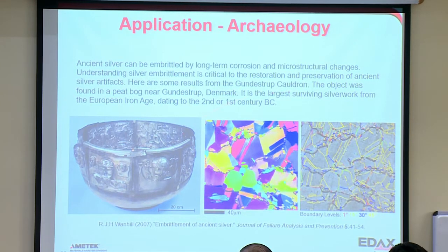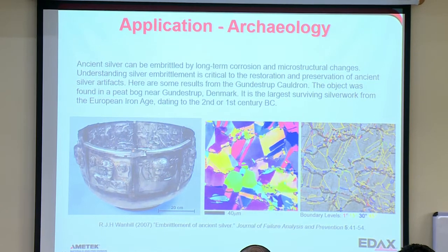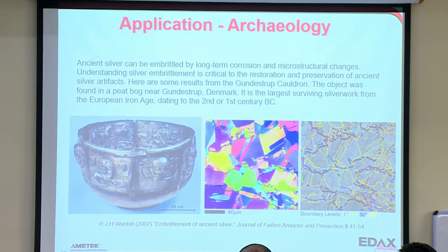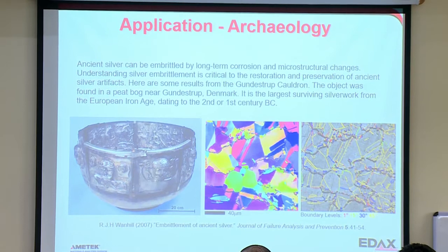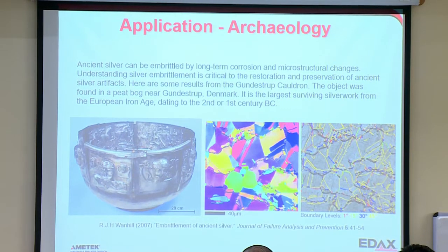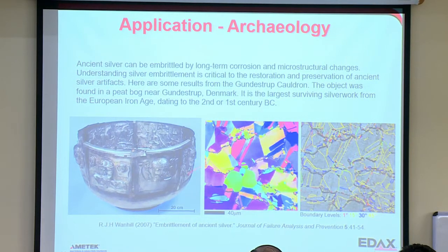called the Gundestrup Cauldron. It came out of the peat bog, and it's starting to fall apart as it's been exposed to air. And so they actually took a little piece of it, put it in the microscope to try to understand what's happening to it. And you can see it's starting to corrode primarily at the grain boundaries, although there is some transgranular corrosion as well. I don't know if this has helped them solve the problem, but it's kind of an interesting study. At least they know why it's happening.